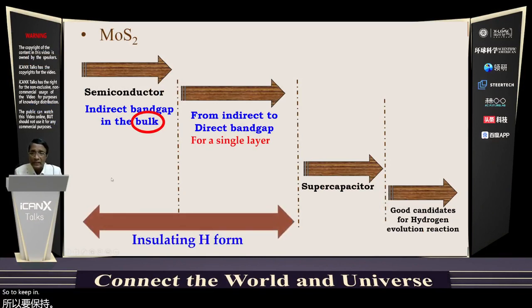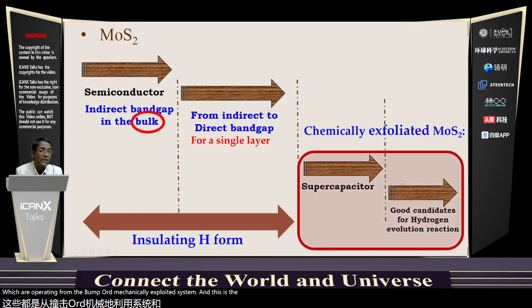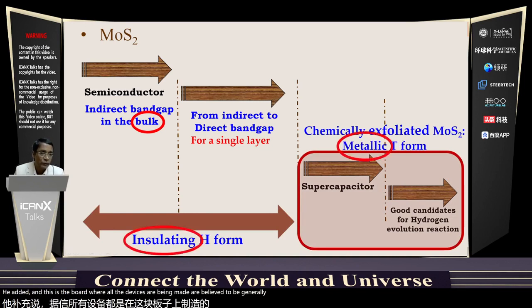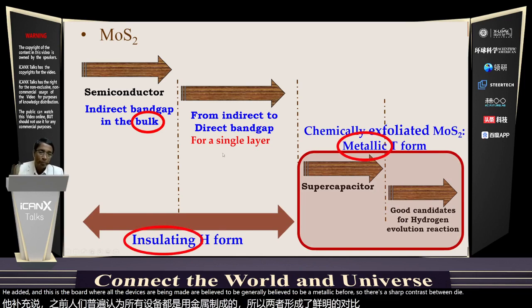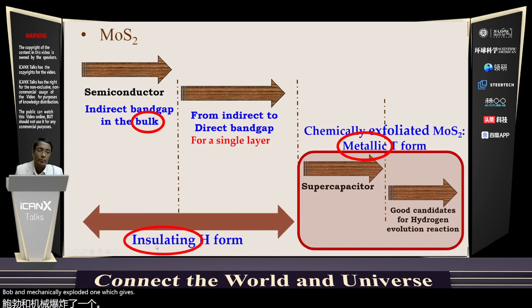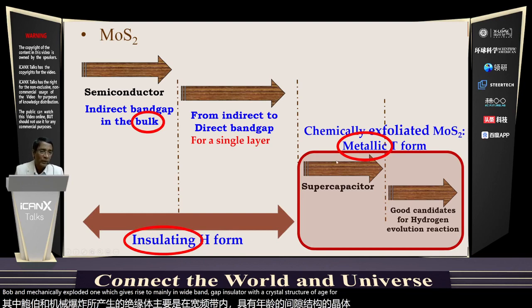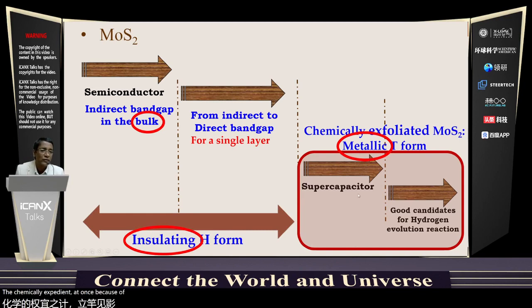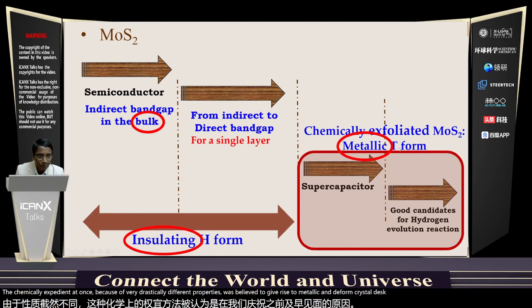So to keep in mind, this is the insulating form, with a very large band gap, which is obtained from the bulk or the mechanically exfoliated system. And this is the part which is chemically exfoliated, and this is the part where all the devices are being made, which is generally believed to be the metallic T form. So there's a sharp contrast between the bulk and the mechanically exfoliated one, which gives rise mainly to a wide band gap insulator with a crystal structure of H form. The chemically exfoliated ones, because of very drastically different properties, were believed to give rise to metallic T form crystallography. Now, why did that happen?